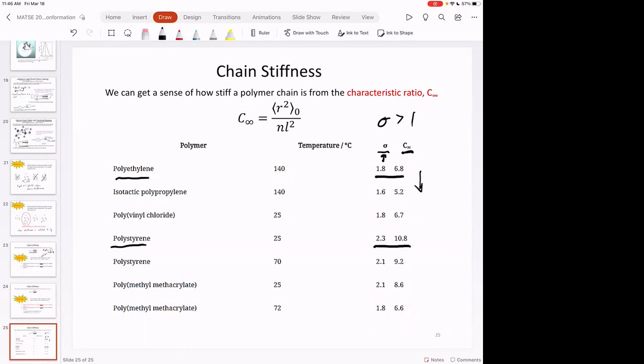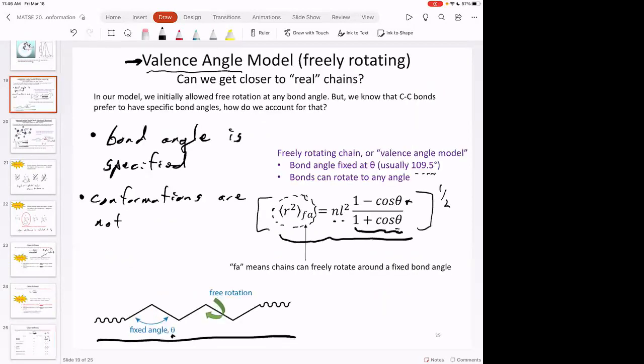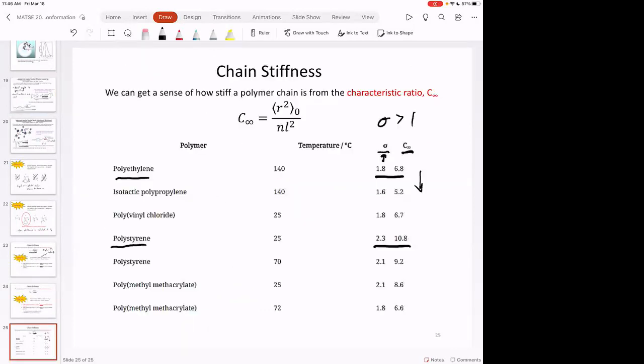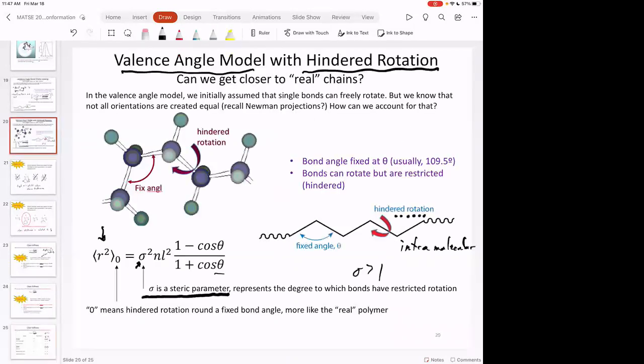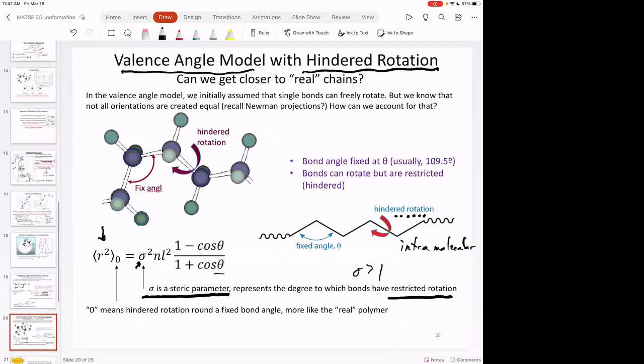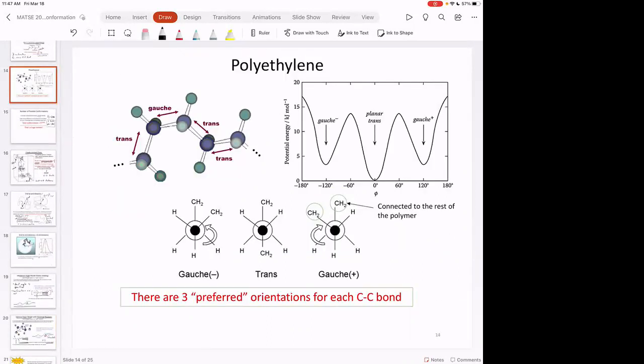Does any polymer have a steric parameter of 1.0 on this table? No, it doesn't. Which means what? A steric parameter of 1 means that we have our freely rotating chain model, right? And any steric parameter greater than 1 means what? There's going to be some favored conformations, even in something simple like polyethylene, because this steric parameter, sigma, talks about restricted or hindered rotation around carbon-carbon bonds. So even polyethylene is going to have favored conformations based on this very simple model of what's planar trans and what's gauche, and it's going to have some high energy conformations, which are not going to be favorable.